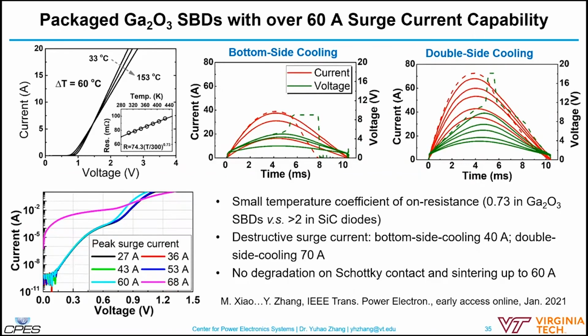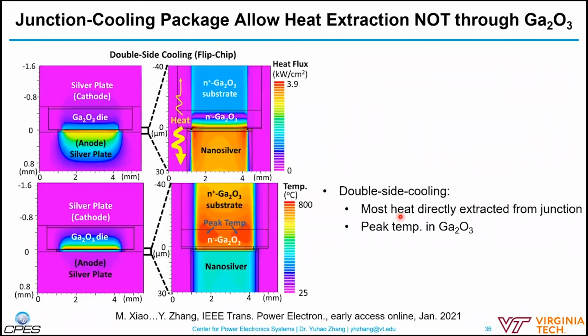It essentially fails at a peak current of about 70 amps. Which means that, particularly during this transient, the Ga2O3 will confidently sustain a peak temperature up to 800 degrees C without any problems. Okay.